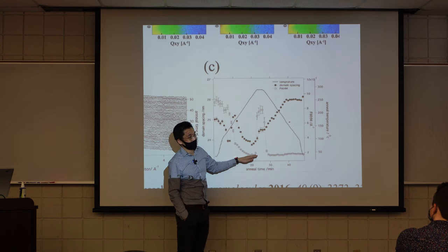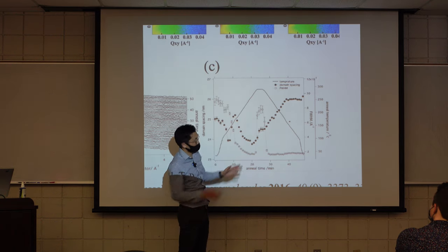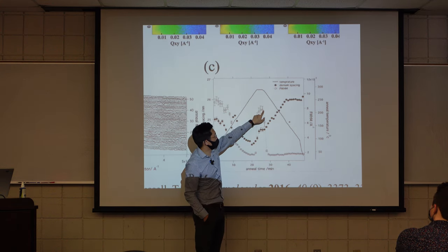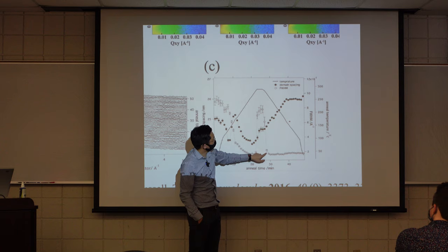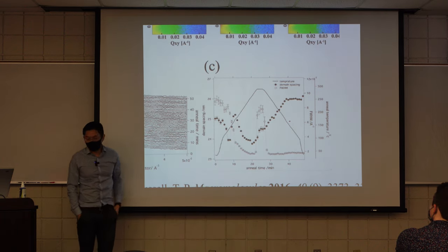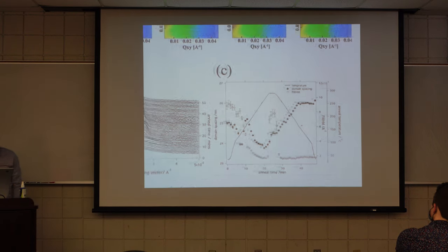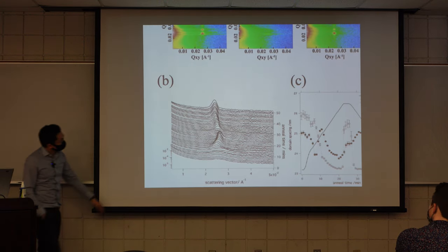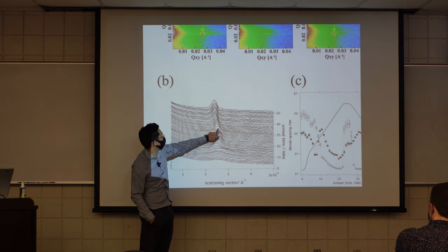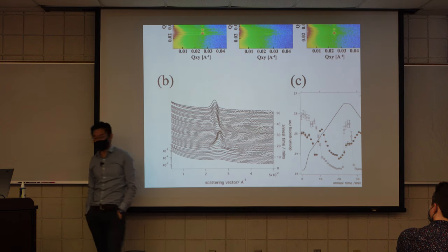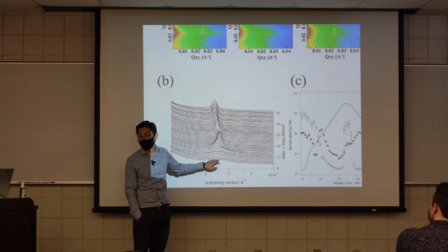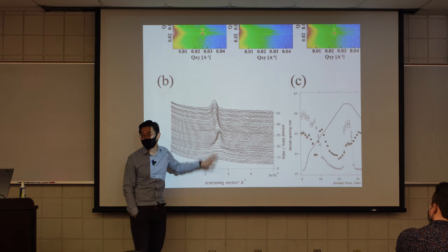And once you heat past the disordered state, the peak suddenly gets widened. It rises so rapidly to a disordered state. Then when you cool it down, it can go back to the ordered state again. Okay? So as you can see, the 1D curve is shown here: peaks, ordering happened, disorder, and now it orders again once you heat and cool. This explains what you need to watch out for when you do an in situ heating or cooling experiment.